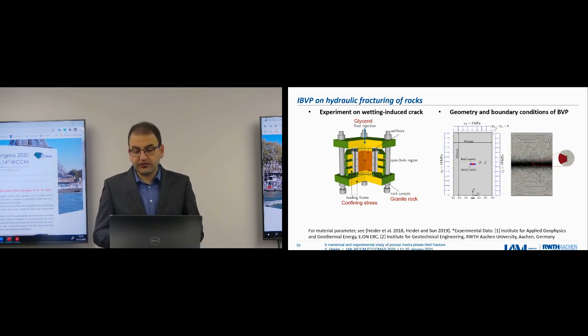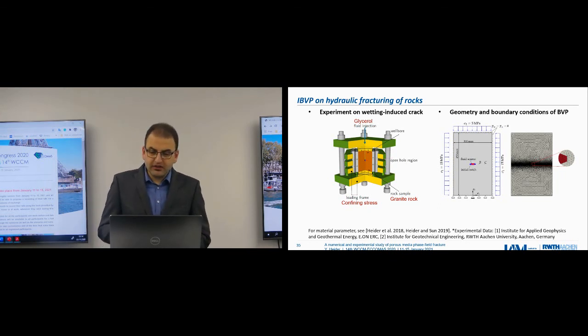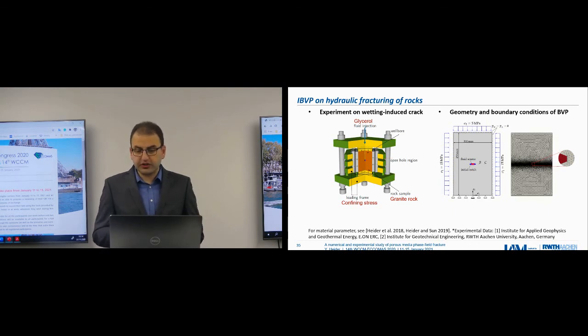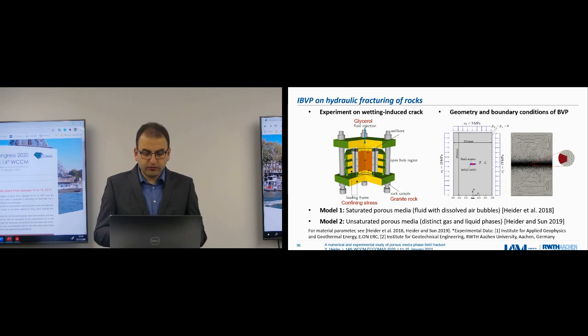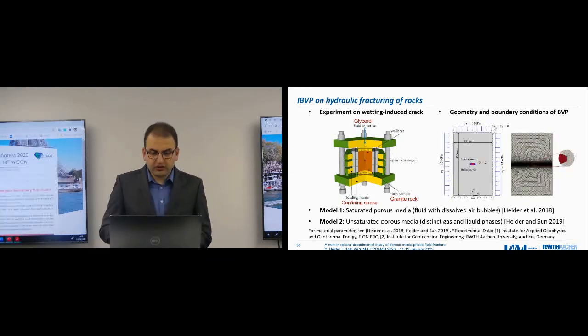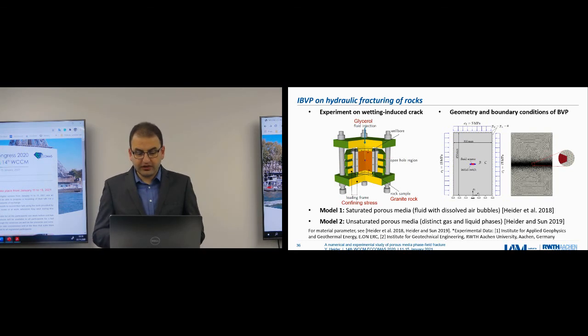And this is an illustration of the model. It's the 2D, but we have also 3D. It shows the stresses at the boundaries and the mesh refinement. We refined the mesh at the beginning in the location where we expect our crack to be propagated. So we have two models. The first model is with fully saturated porous media, but the fluid is compressible as we have dissolved air bubbles. And the second model is unsaturated porous media, where we have gas and liquid phases.